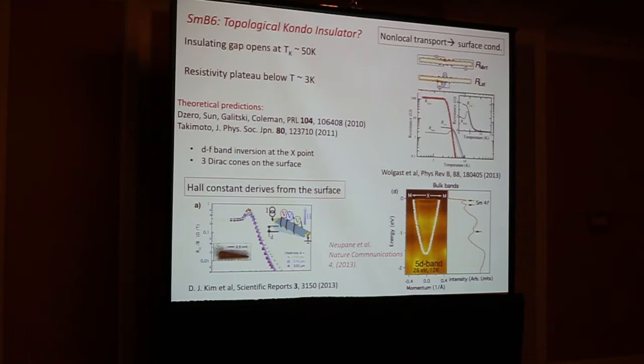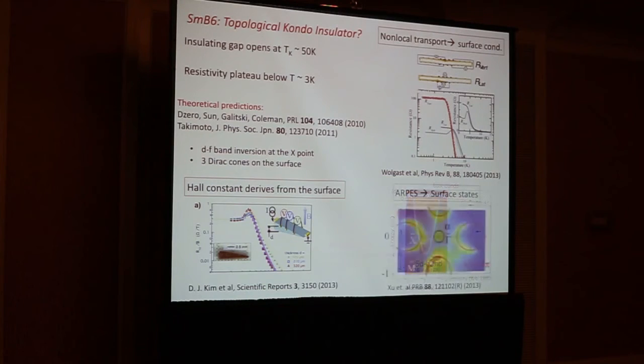And therefore, if this were a non-interacting system, it would be game, set, and match. This would be definitely a topological insulator at low temperatures. You can look at ARPES, and you can also try and look at momentum resolution, and there are definite signs of surface states. This is really pushing ARPES to the limits of its resolution to see these surface states.